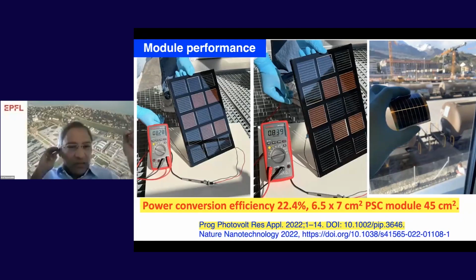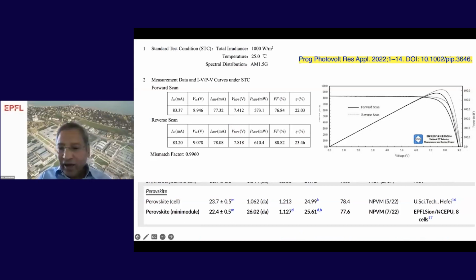So the perovskite mini modules in our group, we made several of these mini modules, including flexible ones. The 22.4% is the highest efficiency in our group in this surface area of 45 centimeters square, which entered into Martin Green's special issue of high efficiency mini modules. 24.4% efficiency, sorry, 22.4% efficiency.